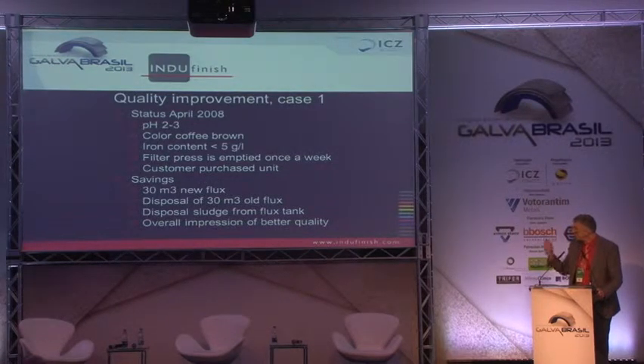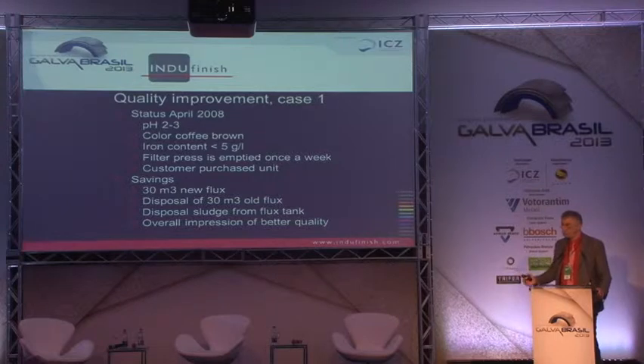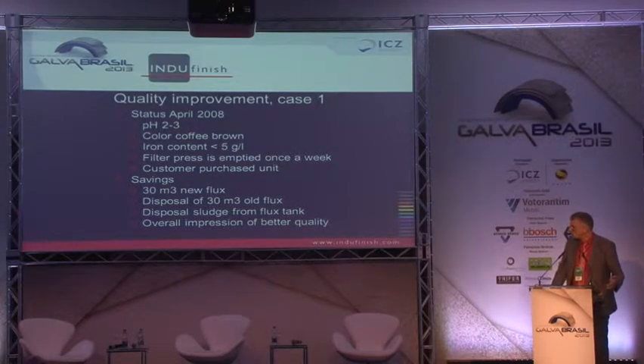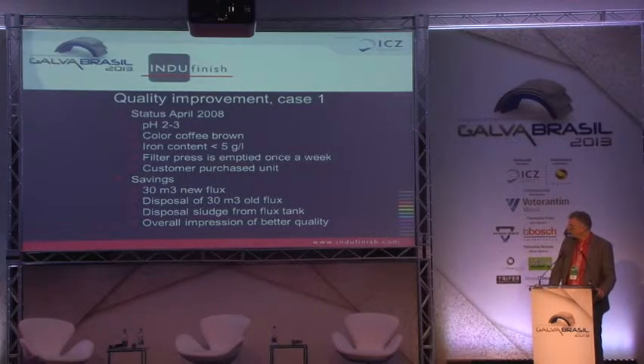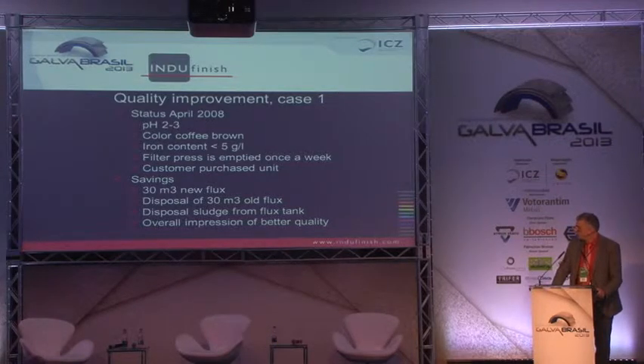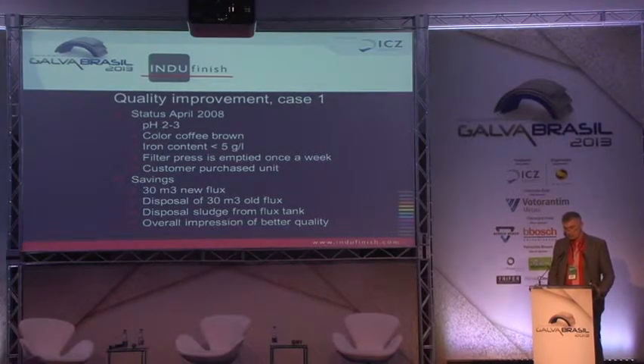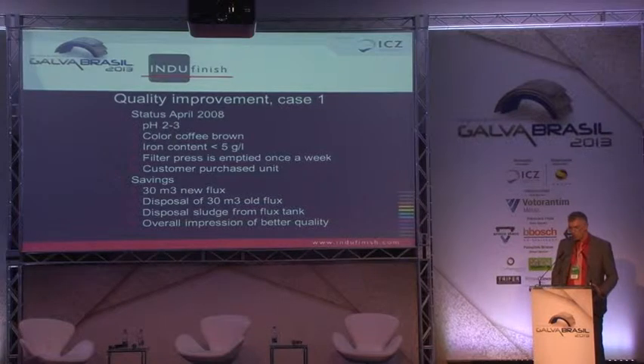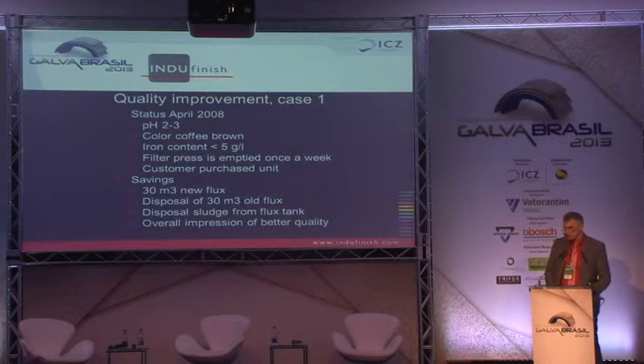April 2008, pH between 2 and 3. Color coffee brown of the flux, like it should be, less than 5 grams a liter, and the filter press was being emptied once a week. We have only one size flux cleaner. One size fits all. Only the size of the filter press is different. If you are doing 7,000 tons a year, you will need a smaller filter press than for 60,000 tons. But you can also use the same flux cleaner.